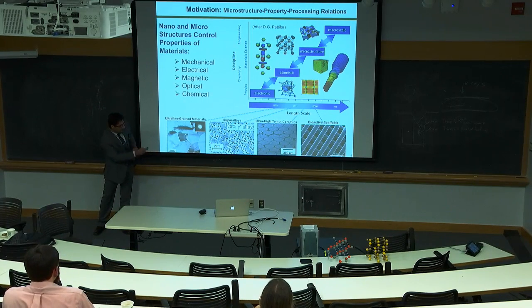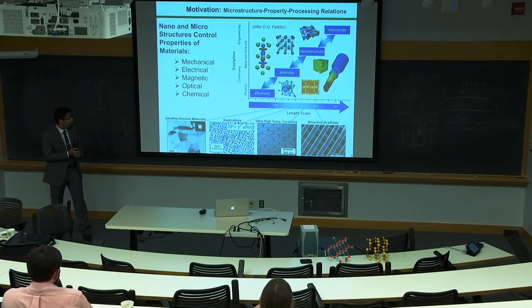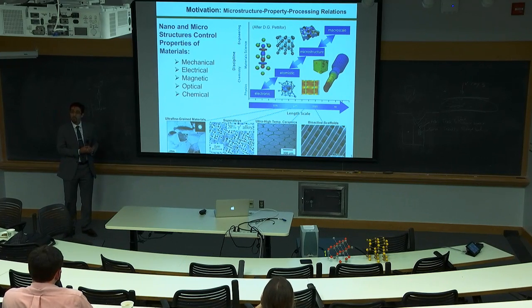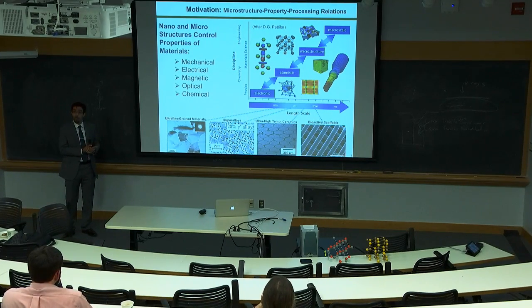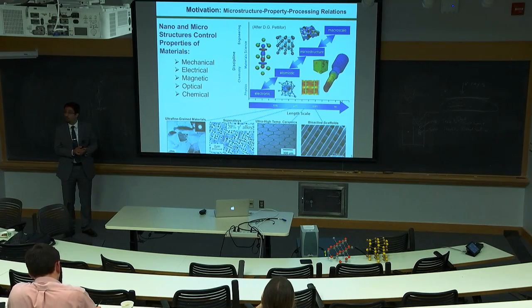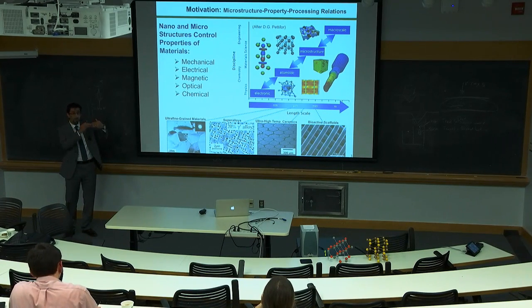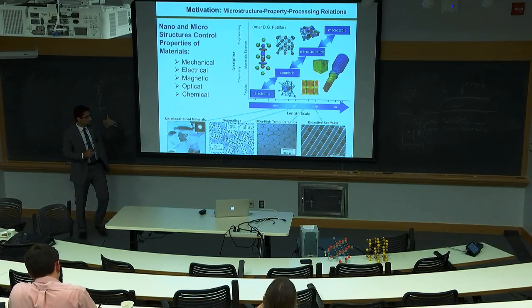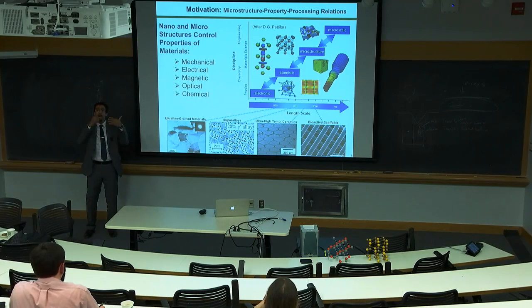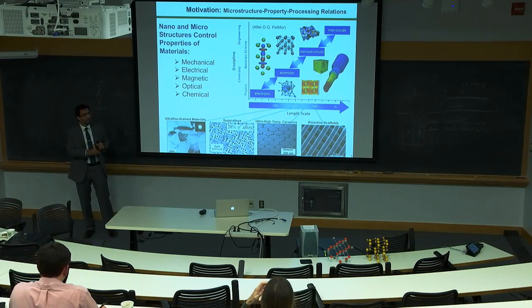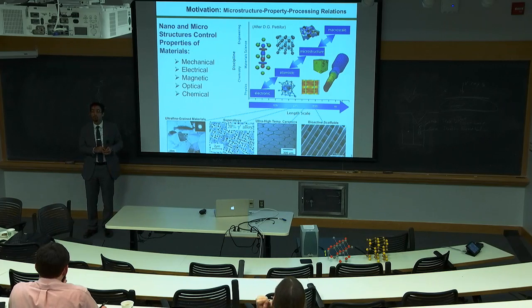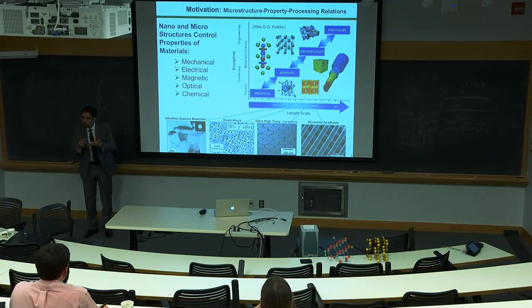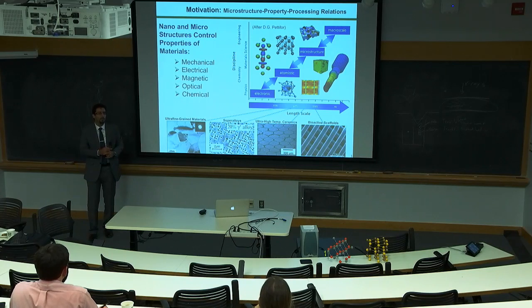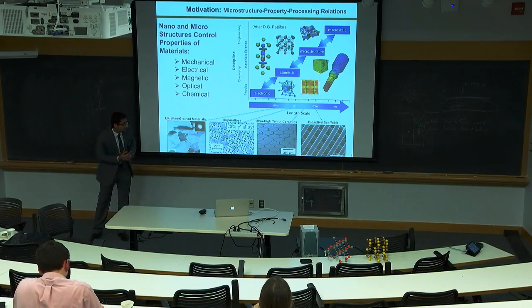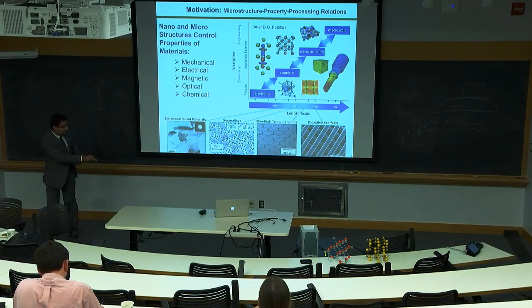This particular example shows the architecture of an ultra-high temperature ceramic material we designed for thermal protection system of aerospace shuttles. So they go at very high temperatures when they want to go outside of the Earth or when they're coming back. So they are ceramics because they have very high melting temperature, but since they're ceramics, they have very low fracture toughness. So we wanted to design an architecture to increase the fracture toughness of those materials. And at the end, you see a bioactive scaffold. You see 1 millimeter length scale.